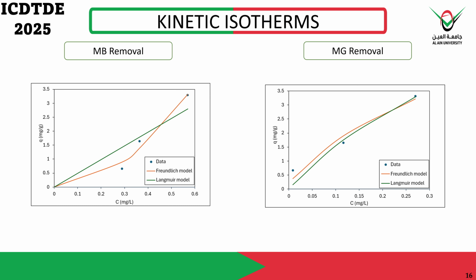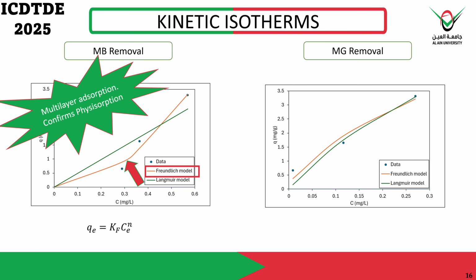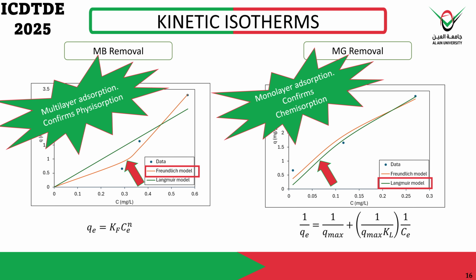In the legend, we have our data in blue dots, the Freundlich model in orange, and the Langmuir model in green. Isotherm analysis for MB shows us that the Freundlich model fits our data better, which means multilayer adsorption, which confirms physisorption. And for MG, our data shows that the Langmuir model fits it better, which means it's monolayer adsorption, which confirms it was chemisorption.